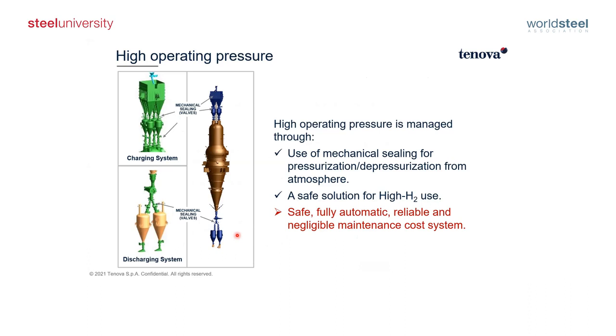And even if it would, the only need would be to replace the normal carbon steel with some other material. Costlier, austenitic stainless are the first choice when needing to improve this. But thanks to the scheme and thanks to the pressures and temperatures inside the module, we simply don't need. And the HYL module are designed in a way that all the areas that contain process gas, so hydrogen in the language of today's presentation, are isolated by mechanical sealing.